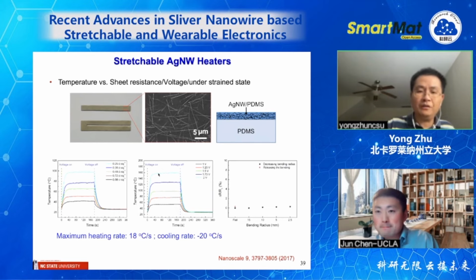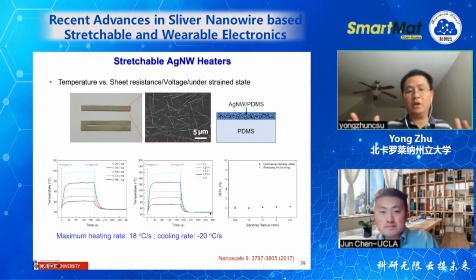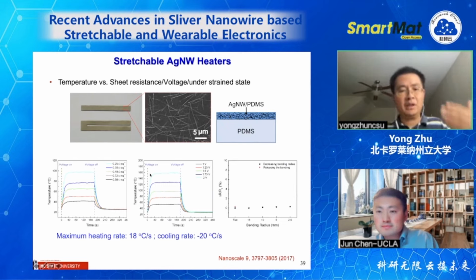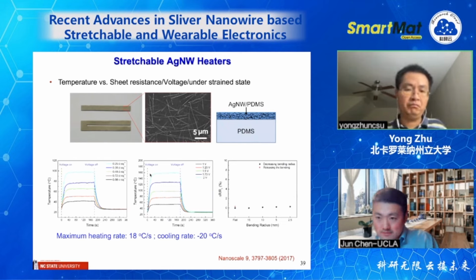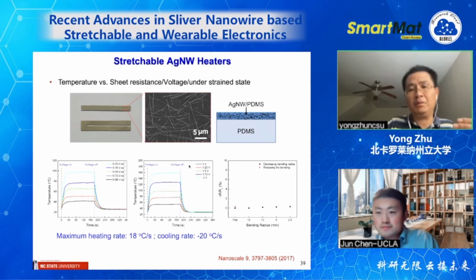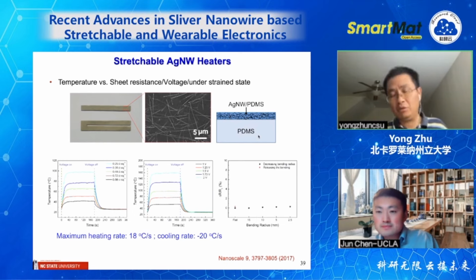If you turn it off, everything will go back, because 160 degrees is still far from the melting temperature of silver. It's also far from the melting temperature of PDMS. PDMS can easily survive 200 degrees C and above. So 160 is not going to cause permanent damage to either the silver nanowire or the PDMS. So the process and the performance are repeatable.